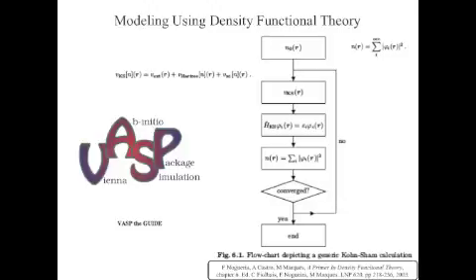Fortunately, density functional theory states that everything you need to calculate the ground state properties of the material can be written as a function of the electron density. So if you're doing DFT calculations, you can use a software like VASP to take your initial inputs and an initial electron density and then converge that through the Kohn-Sham equations and get to a converged solution, and then you have the ground state electronic properties.